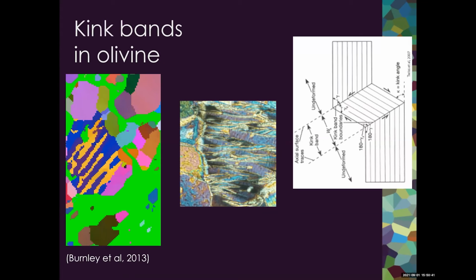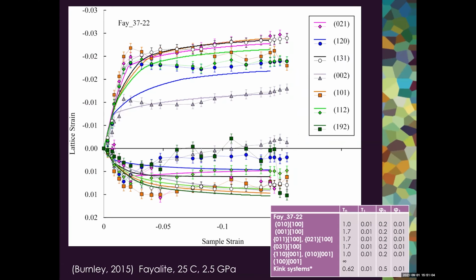And so if we add kink band formation, which is the low temperature accommodation mechanism, we can target the grains with kinks, which tend to have their 001 axis parallel or near to compression, and we can soften those grains. This is just some EBSD work that was done on magnesium germanate olivine grains, where we can see this kink banding. And this is just another micrograph showing the similar kinking. When we include the slip system combination and kink band formation into the model, we're able to match our diffraction data much better.